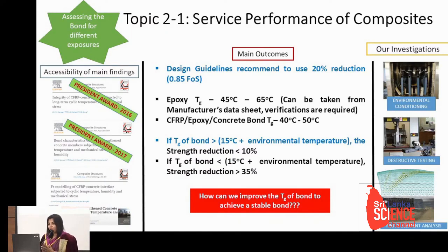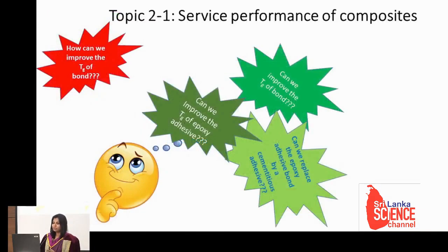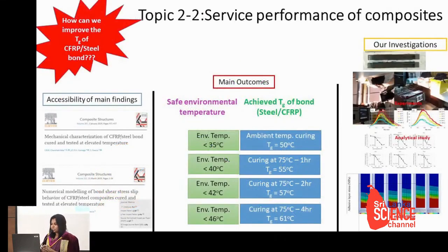Then the next question came, how can we improve the Tg of the bond to achieve this stable condition in service? So we thought, can we improve the Tg of the epoxy adhesive or the Tg of the bond? Or can we replace the bond using cementitious adhesive? So first, we thought to apply the elevated temperature curing technique. Researchers have applied it for some other materials, products, and strengthening samples, but we thought to see whether this technique will work with our composite. This is the common application, CFRP steel bond. So we thought to apply it for CFRP steel composites and see whether it works.